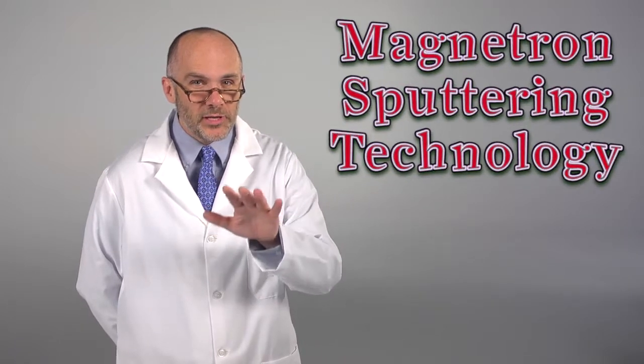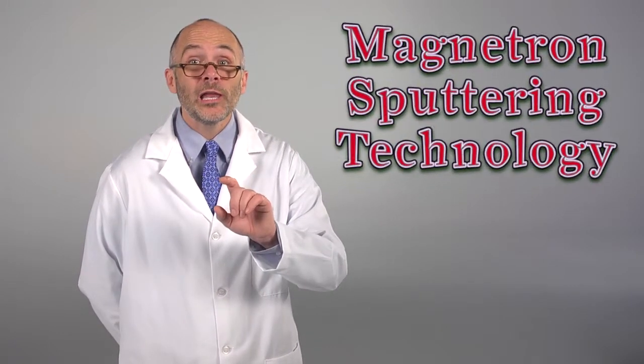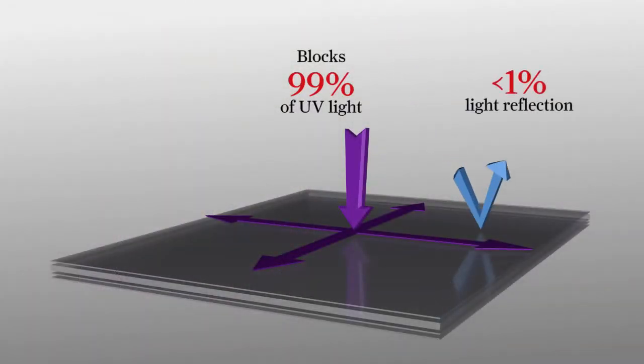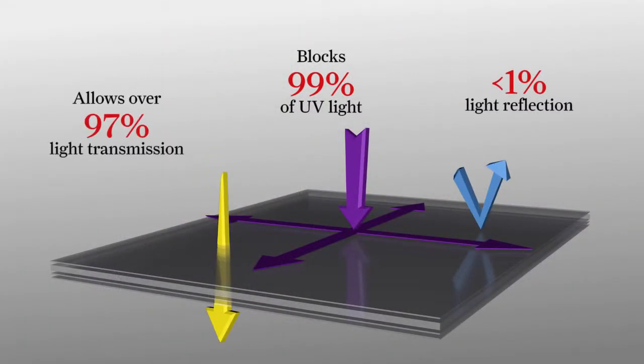TrueView's proprietary anti-reflective coating process uses Magnetron sputtering technology, where controlled layers of highly energized metal oxides are deposited onto the glass and permanently bond to the glass substrate. With less than 1% light reflection and over 97% light transmission, this virtually invisible glazing will enhance colors, brightness, fine details, and contrast levels of all types of artwork.